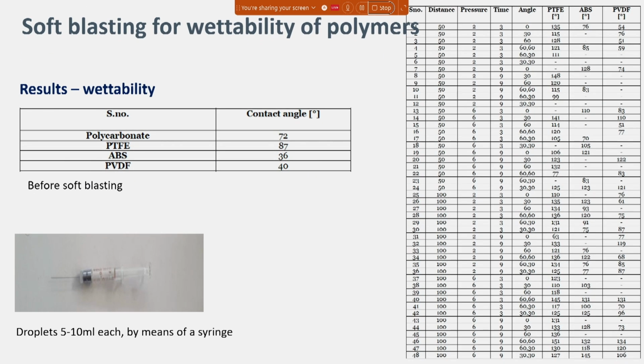And this is the same in terms of wettability. So in terms of wettability, we start from a contact angle that is this one. And we can notice that all the materials that we have considered are hydrophilic. Okay, they are hydrophilic because the angle is anyway less than 90 degrees. Even PTFE that is 87 does not reach 90. The drop was arranged by means of this syringe, 5 milliliters each drop.